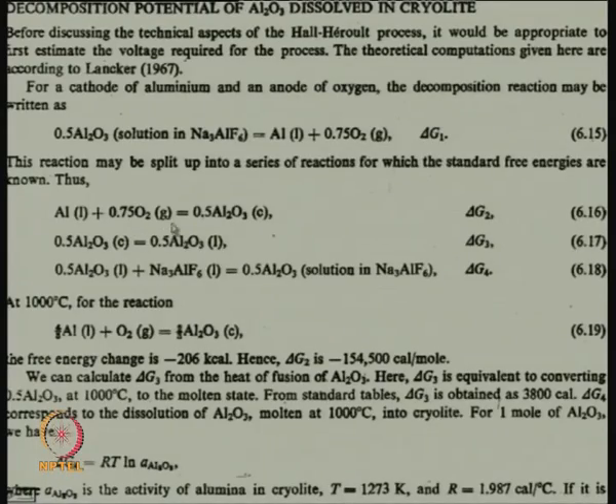So, we have split the reaction into three. Firstly, the formation reaction, then the state change reaction, then dissolution. We will find these values, then add them up to get this value. Now, at 1000 degrees for the reaction aluminum plus O2 giving Al2O3, the C again being solid, we get from our Ellingham diagrams the free energy change, which is given per oxygen molecule. So, you have to recalculate it here for 0.5 Al2O3, that is given as minus 206 kilocalories.